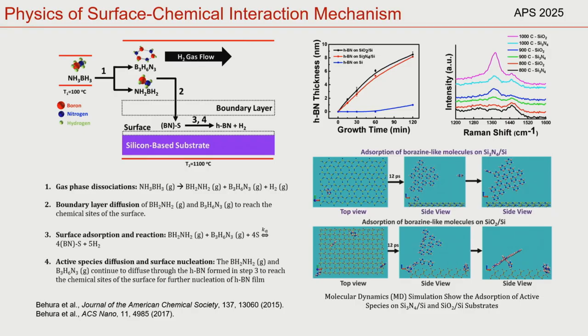As you can see here, the boundary layer is directly influenced by these changes in our growth parameters, such as temperature, growth time, pressure, and the like. So we are able to take the vapor phase of the ammonia borane complex as it becomes products like borazine and other polymers of the like. And then once it gets into that vapor phase, we allow for that boundary layer to be readily deposited on by increasing that temperature, increasing that growth time. We create the conditions necessary for borazine to actually adsorb on the surface and react with each other. And from there, it can nucleate out.